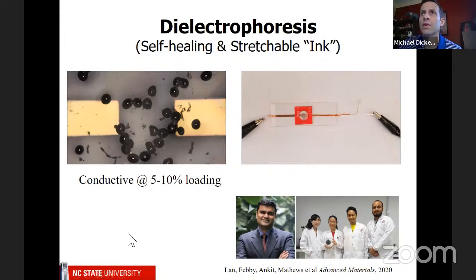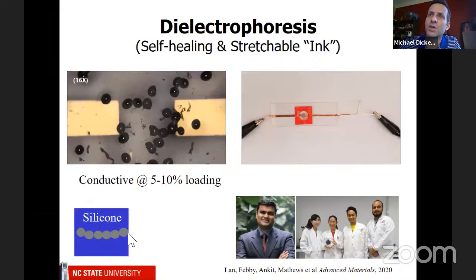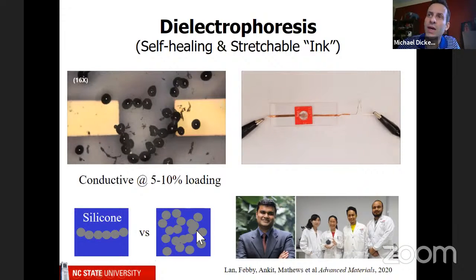Maybe I'll play it one more time because it happens quite quickly. If you watch the bottom of this video, you see that the particles merge together, and because they're liquid, they will actually sinter. They'll stick together and form a conductive path. The beauty of this is, in previous literature, usually you have to add many particles to make a good conductor. In our case, we only have to add a few because we can assemble them using electric fields.